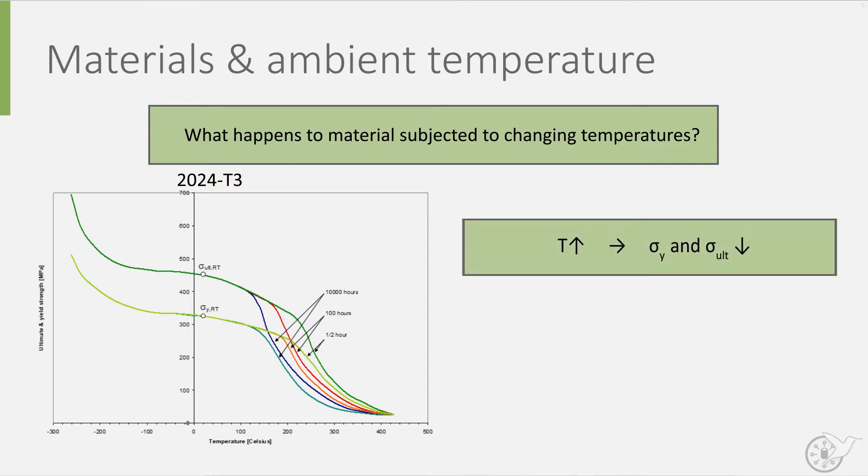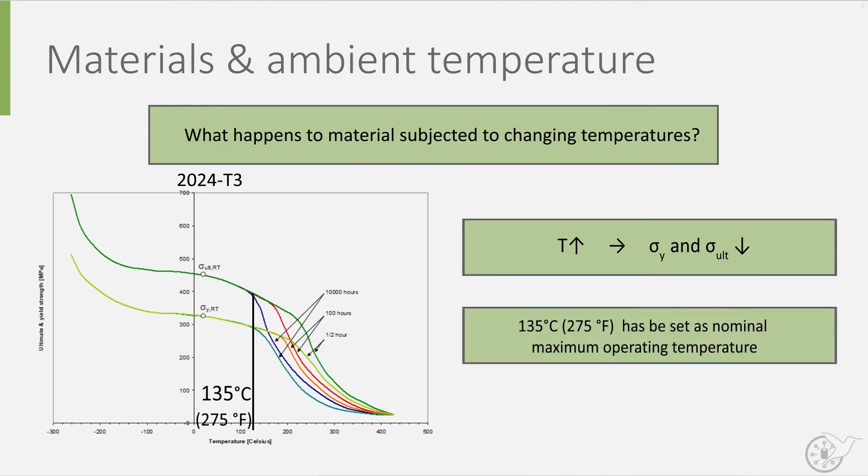Both rapidly degrading after 135 degrees Celsius, which is why this temperature has been set as the nominal maximum operating temperature.